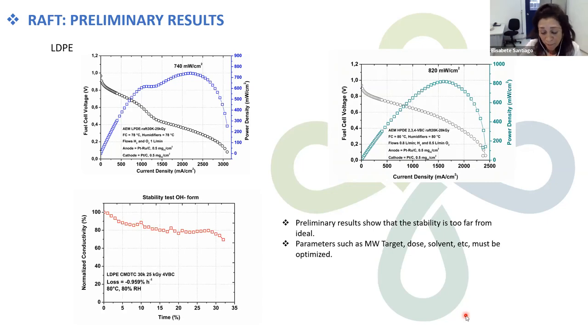But in terms of performance, the performance is so far from the values obtained for conventional grafting, indicating that the synthesis parameters must be adjusted and optimized. In terms of stability, our preliminary results show that stability is too far from the ideal. But it is shown that you need to change parameters such as molar weight, target, dose, solvent. These parameters must be optimized to achieve higher performance and higher stability.